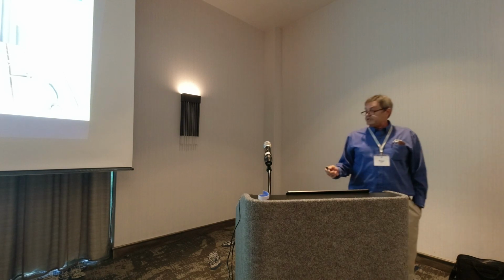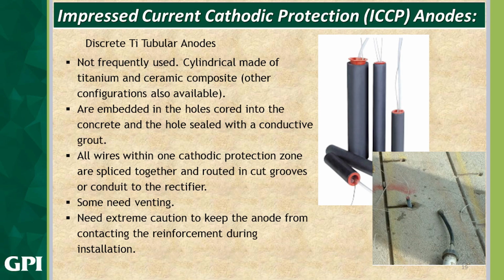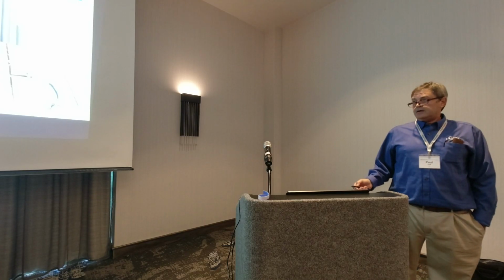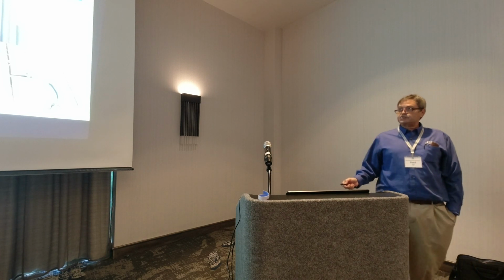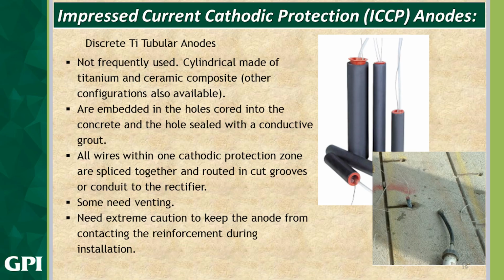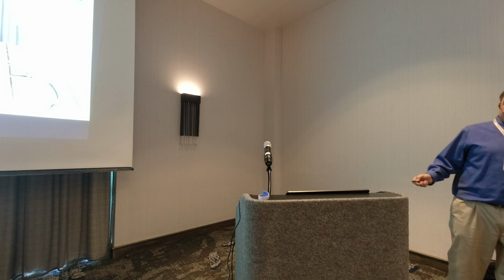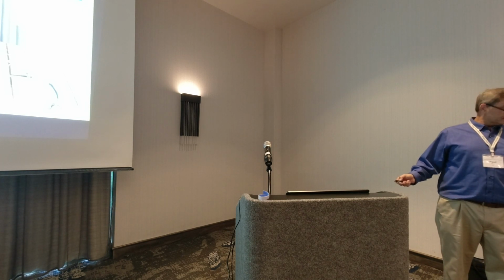Let's move to discrete tubular anodes. These are also for ICCP. These are not all that frequently used. They're cylindrical, made of titanium and ceramic composites. They're embedded in holes cored into the concrete and sealed with a conductive grout. Same thing again, we need a conductive grout to get our current out and back to our steel. All the wires within one cathodic protection zone are spliced together and routed into cut grooves and then into conduit to the rectifier. We need extreme caution. You don't want your anode contacting the reinforcement. That's a no-no.